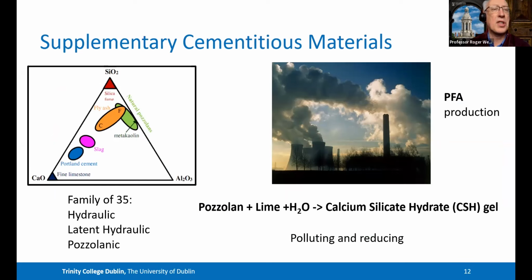And this little triangle on the left-hand side shows the oxides which comprise the constituents of cement. Portland cement, which is the fundamental cement we've used very successfully for many years, is there, and there are many alternatives. Some of the primary ones are here, such as slag, for example GGBS, and fly ash, used very successfully in some countries. And then perhaps some of the more recent ones, such as metakaolin. These are cements which are being investigated by a large number of people in order to see whether or not they can replace Portland cement because of its high carbon footprint.